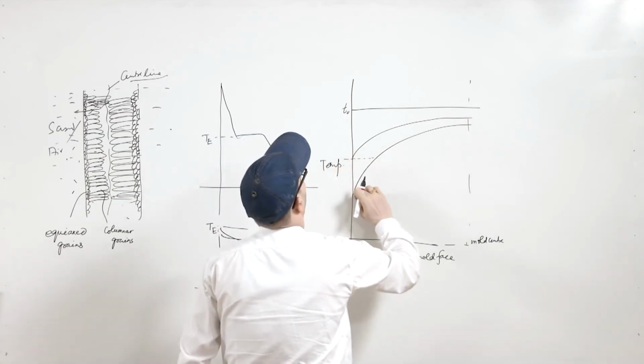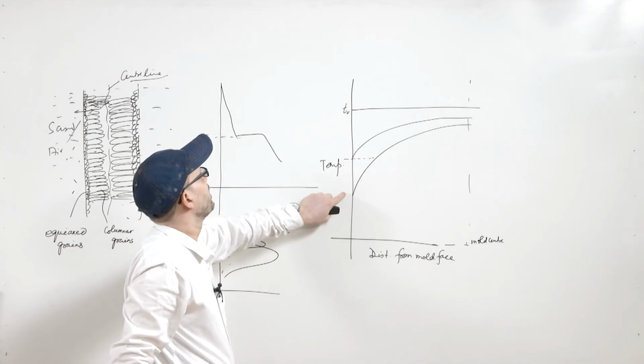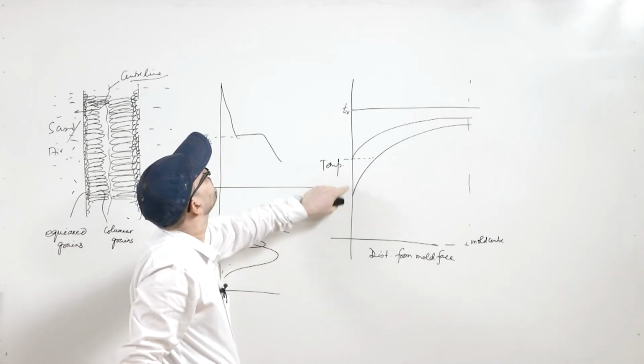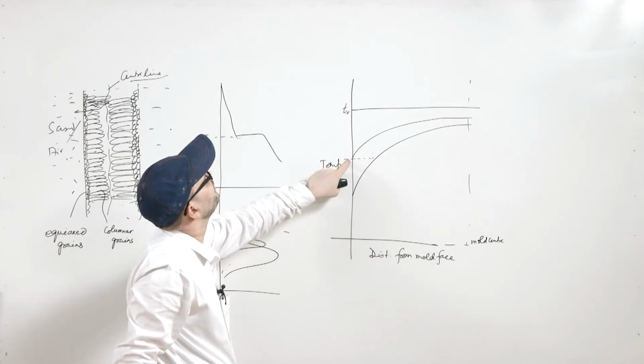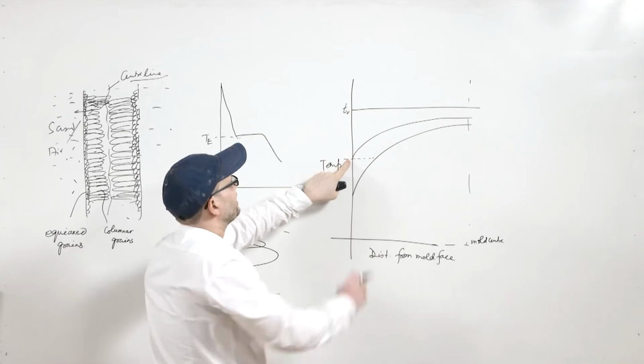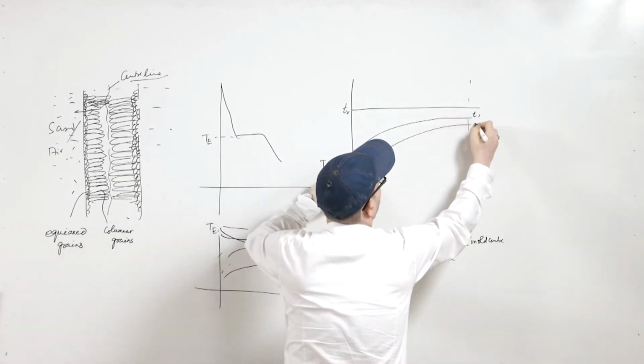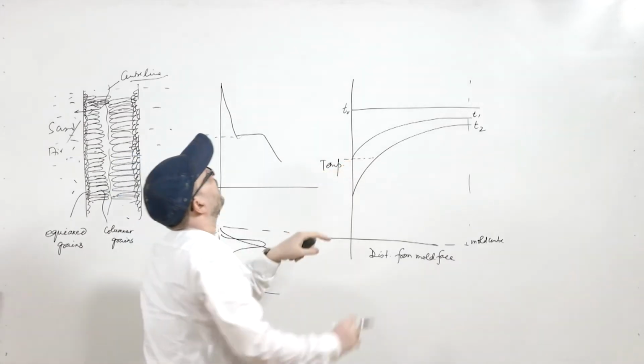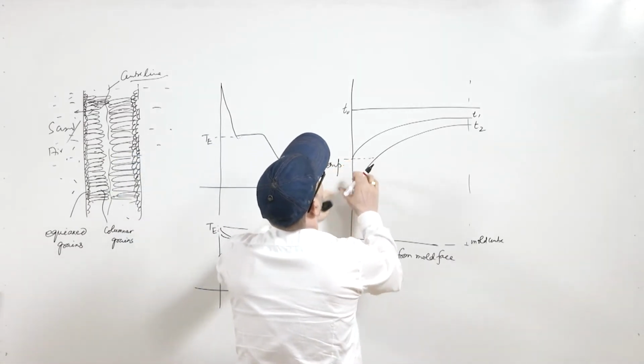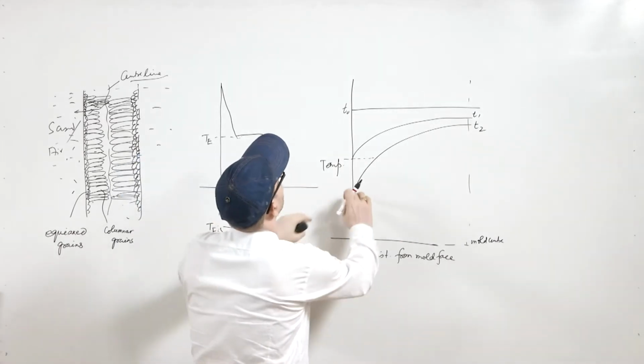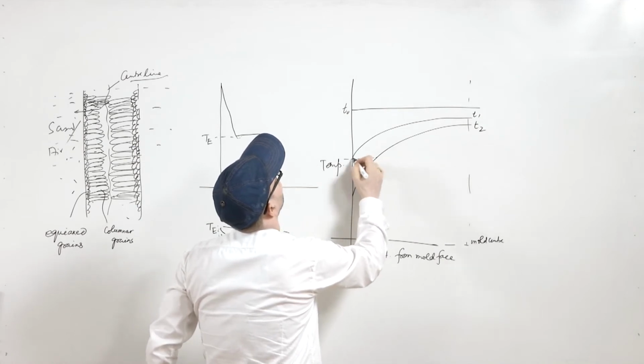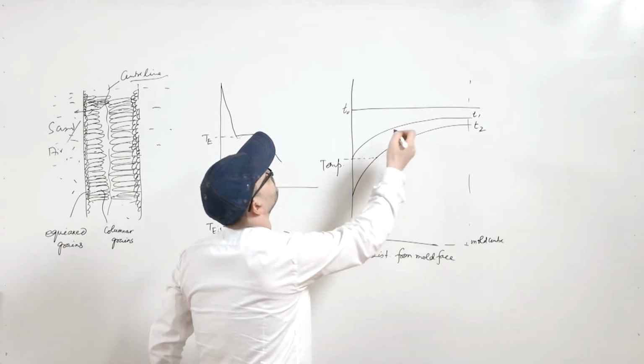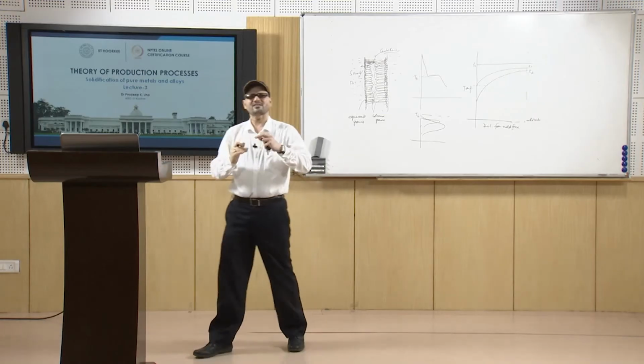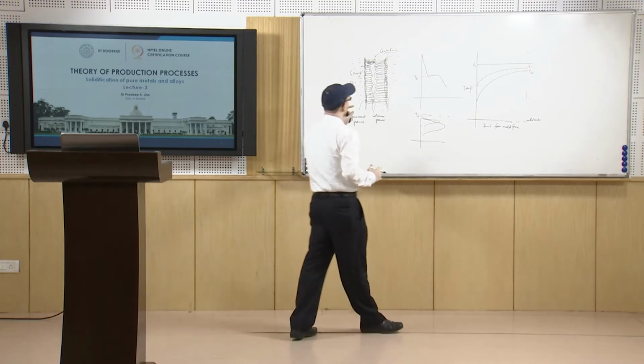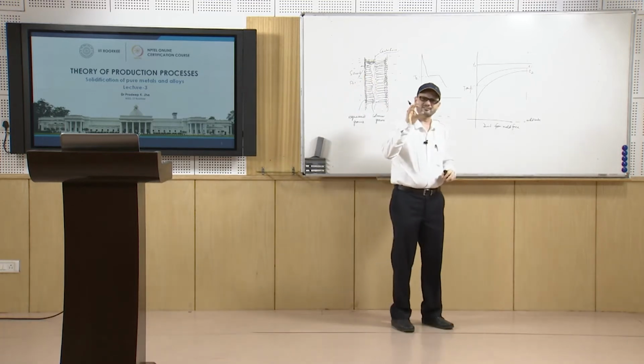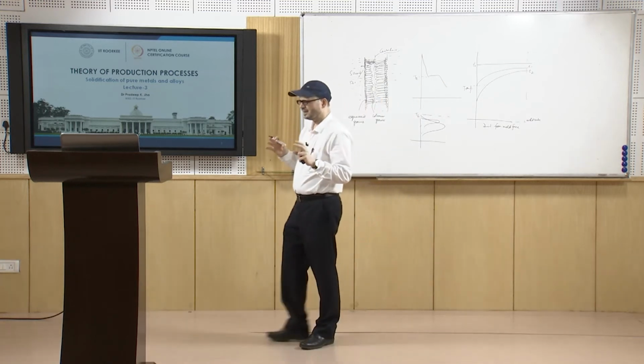So, this way at the center you have temperature, at the mold face the temperature is becoming quite less. So, the solidification has started here itself. At this time itself, at the face the solidification has started, whereas here in this case that is not the case. Here already it is solidified, and at this point the temperature. So, here at this point the solidification will start. So, this way as the time progresses you see that there will be more temperature in the central region.